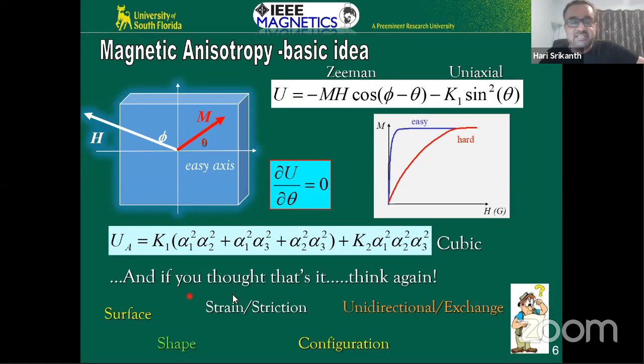Strain is important, especially if you have interfaces. When you have thin films, for example, you can have substrate strain that affects the magnetization of the magnetic film, and that can be used for determining, again, the preferred orientation and the way in which the magnetization curve approaches saturation. Configuration is something important. You can actually couple different kinds of magnetic particles or even non-magnetic metallic particles with, let's say, magnetic oxides, and you can form these clusters. And these clusters have a geometric configuration, and using that, you can also manipulate the magnetic characteristics.